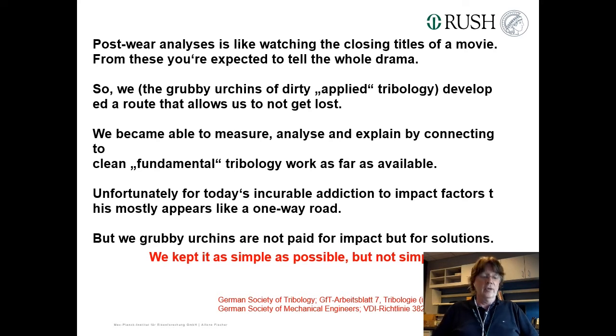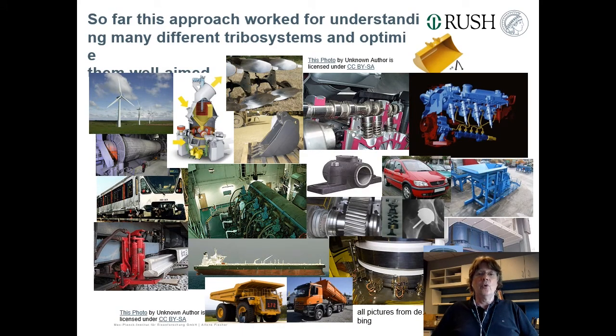That depends on the part in the tribosystem you're dealing with. So we kept it as simple as possible. Mechanical engineering has to be simple, but not simpler. We even have some papers on it, some German standards, and by the way, both of them are in English as well. And I can only tell you, it worked so far. It worked in understanding many, many different tribosystems, very big ones, very small ones, and to optimize them without running too many tests. In most cases, we analyzed worn parts and the materials, and the alterations on the surface, and especially below the surface, told us a story whether you are sailing very close to the waterfall or whether there is a certain safety margin still possible.